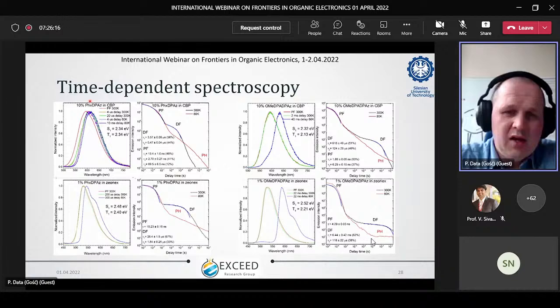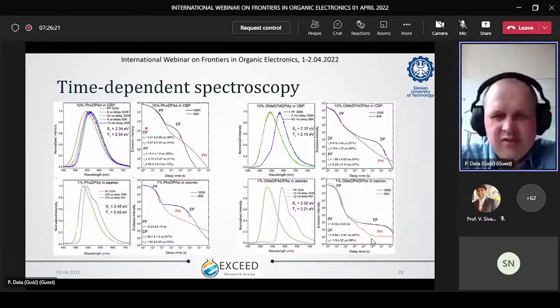What else? We can see that here the delayed fluorescence component, if you integrate this value, its contribution is much smaller than in the case of the polymer matrix. So there is another factor in the literature, the DF-PF ratio. It shows the delayed fluorescence contribution. It's a simple integration of this transient curve over the delayed fluorescence or prompt fluorescence emission, and you divide those values.